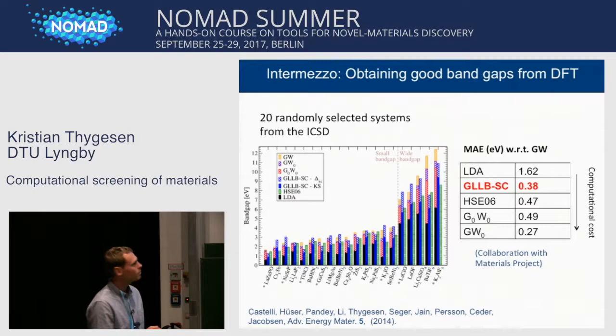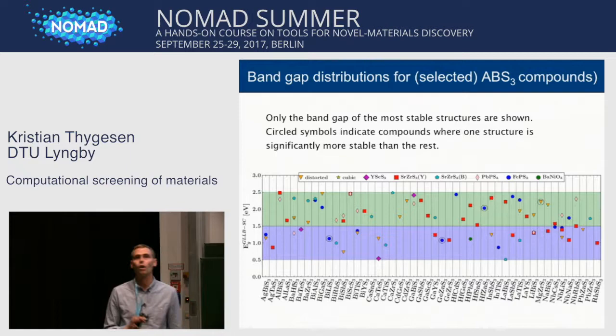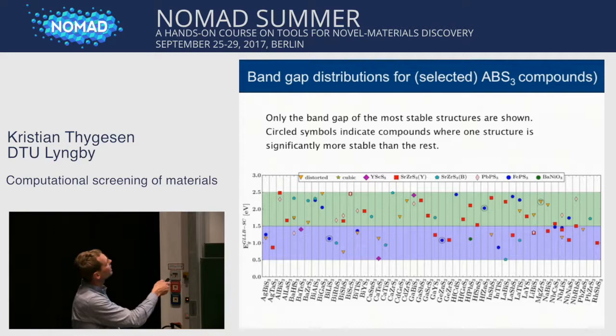So using that functional, we are now calculating the band gap of all the materials that are left in this screening study. And you can see again here the different phases, the different structures we're interested in. And this is just a subset of the materials that we have at this point of the screening. And we have the band gaps here of the most stable structures. There might be more than one structure if they are within 25 meV in stability, then we have more structures with the same stoichiometry.